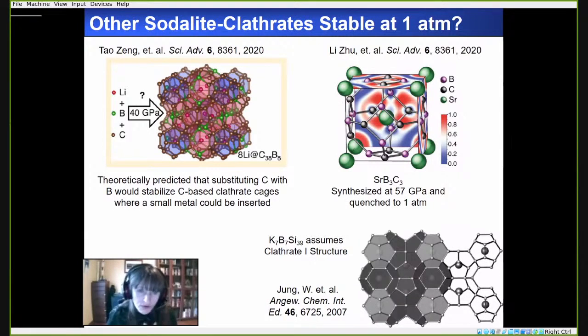However, it was proposed based upon theory in this paper right here, that if you dope a carbon lattice with boron, and then add small alkali metals to it, you could potentially stabilize these carbon-like lattices under pressure. And then most recently, the group of Timothy Strobel theoretically calculated and experimentally was able to synthesize this strontium boron carbide clathrate under pressure and then quench it to 1 atmosphere. So this made us think of, what about borosilicides?